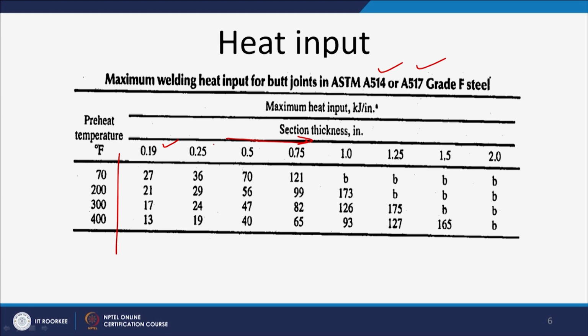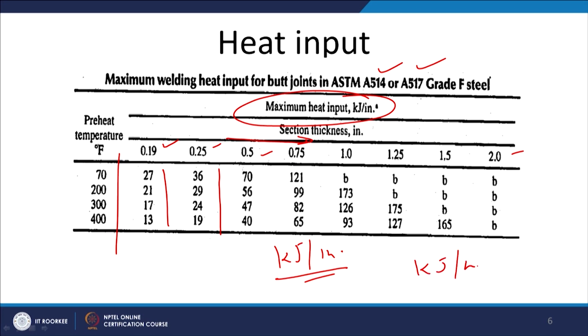Now, we will see there are the different preheat temperatures, different heat input values for developing the weld joints or butt joints of the A514 and A517 steels. Like what we can see here, this is the preheat temperature and the kind of the section thicknesses 0.19 to 0.25, 0.5 to 2 inch, and the maximum heat input which is allowed. So, this is the maximum heat input in kilojoule per inch. So, we can obtain in kilojoule per mm which is most commonly used by dividing these values with the 25. So, this is giving us the value of the maximum heat input which will be giving us the acceptable range of the notch toughness.